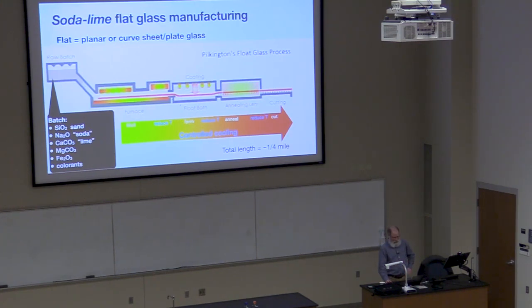So then as you progress down, the glass is formed here into a sheet, formed at the right thickness and the right width. And once again, once you've got the forming right, then you've got to reduce the temperature of the glass to get ready for the next stage, in which the glass ribbon is lifted up on these rollers. And the glass has to be at just the right point that it's solid enough to be supported on the rollers. If it's too solid, it'll be brittle and maybe break. And if it's too warm, it'll sag and maybe drag on this lip or get marked by the rollers. So the glass makers watch this point very carefully. You've got to be within like 10 degrees to get that consistent process.